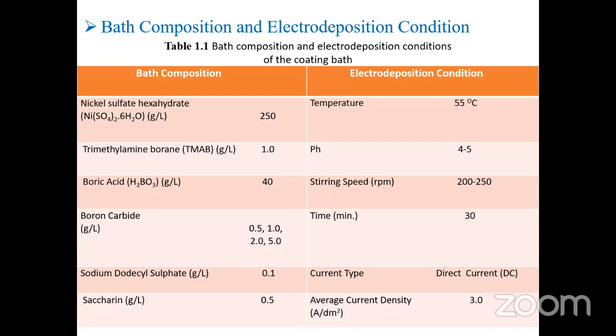Bath composition and electrodeposition conditions of the coating bath are shown in the table. In our study, we used 250 gram per liter nickel sulfate hexahydrate, 1 gram per liter trimethylamine borane, 40 gram per liter boric acid, and 0.5, 1, 2, and 5 gram per liter boron carbide, respectively.